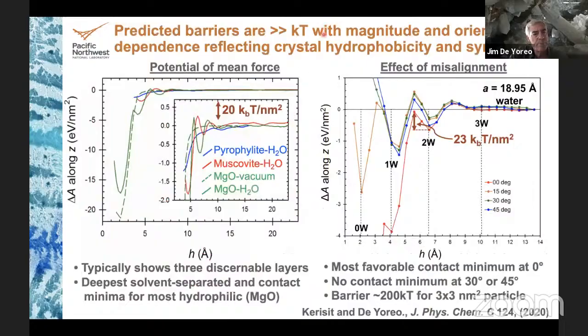Now, what does it do to the barriers? So if we now look at the potential of mean force for bringing particles together, we bring them towards the surface, what you see is a set of wiggles, right? And eventually a drop to a deep minimum, which is the contact. Now, if you look at the size of these wiggles, this is due to the water layer. So this is one water layer, two water layers, three. To get past these water layers, we have to go over these barriers. And these barriers are on order of 20 kT per nanometer squared. Okay, so this I think is the data for MgO.